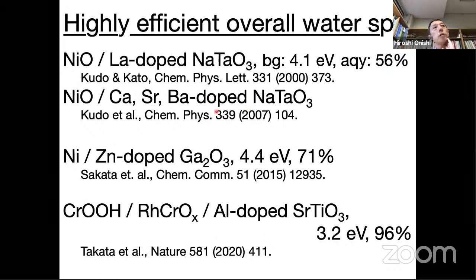Then soon later, the same group found that calcium, strontium, or barium doping to the same host material gave a very similar quantum yield. Some years later, a different group in Japan found that zinc doping to gallium oxide presented an even higher quantum yield for the water splitting, 70%.